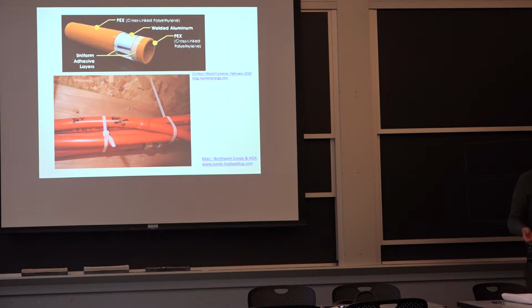It's a relatively thin sheet of aluminum that's bent over and then electroresistance welded. So of course the electroresistance weld is not always perfect. There may be some path there for the moisture to flow, but upon more detailed review, essentially we found that the corrosion of the aluminum was because the pH fell below 3. And the reason why the pH fell below 3 in this case was the complete deterioration of the inner layer.